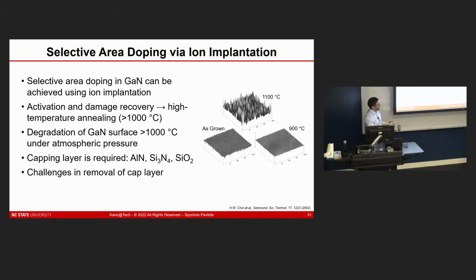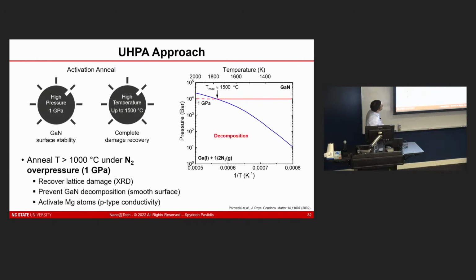So we've been looking at an approach to doing this that does not involve a capping layer. The idea behind this is to use ultra high pressure annealing. So instead of relying on a capping layer to hold the material together, let's heat this material up in the presence of a very, very large nitrogen overpressure. We started off by doing this at 1 gigapascal, so very high pressures, but have more recently scaled this down to a few hundred megapascal.